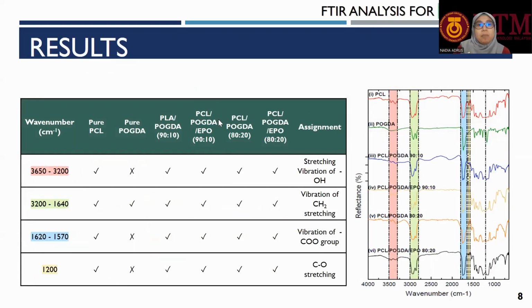Here is the case for the blend of PCL with POGDA. That means we can look into the peak assignment for PCL, pure POGDA, and also the blend. And here again, we can see that when we blend, both characteristics of the peaks for each component can be observed. That consists of assignment for OH at the peak of 3,500, and then the alkyl group at about 2,900, COO group here at about 1,600, and also CO stretching at 1,200.